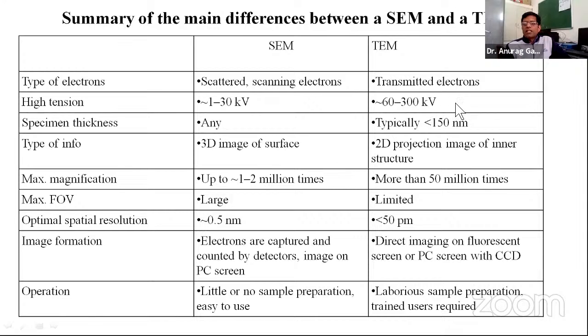And if this voltage is high, naturally the resolution will be better because the wavelength of the electron will be smaller. As for specimen thickness, I told you that in SEM it does not matter what the thickness is, because we are not transmitting the electrons. They are coming from the surface. So any thickness can work for SEM, but in TEM the thickness should typically be less than 150 nanometers, so that the highly energetic electron beam can be transmitted across the sample.